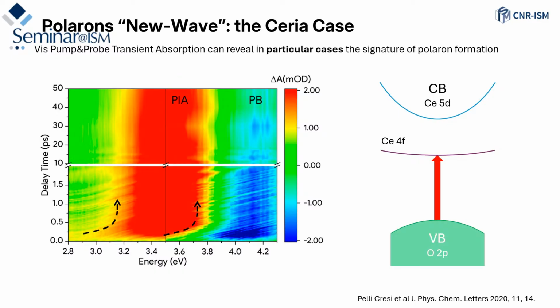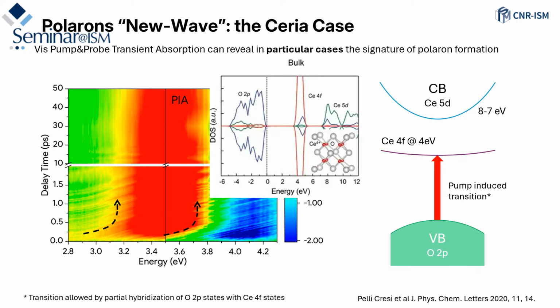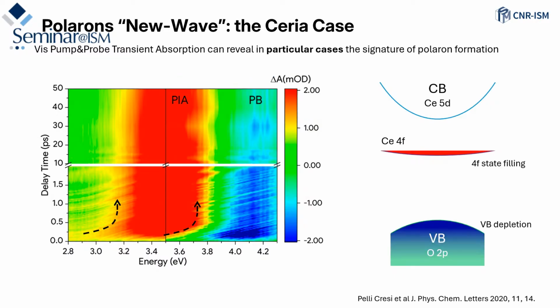However, we have this very nice, very localized state, which can be filled because in principle those states are hybridized with the O2p state. So we can also pump those transitions using a visible UV pump, of course. And if you populate them, here you have the transient absorption map. You can see that we have the depletion of the valence band, which is reported by this negative absorption after the excitation of the system.